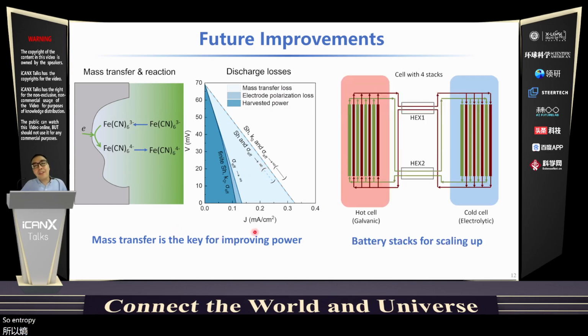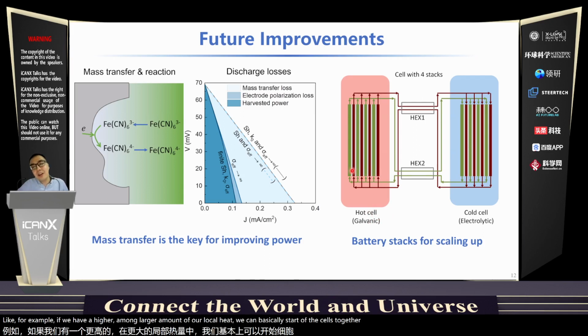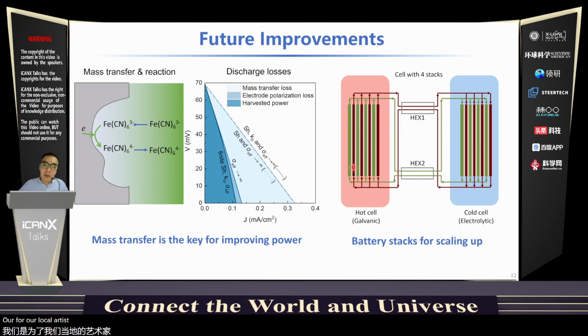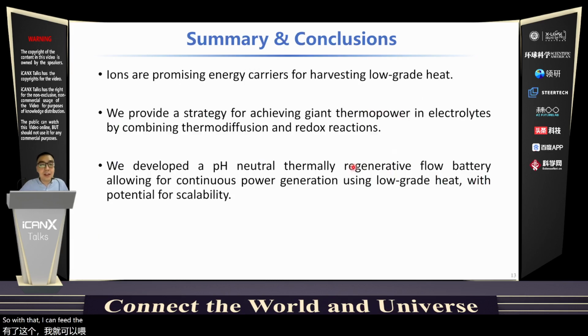After solving this issue, another point I would like to emphasize here is that this method can not only operate stably, it also has the potential for scaling up. For example, if we have a larger amount of low-grade heat, we can stack the cells together. We can scale up the power for low-grade heat harvesting. So with that, I can give the summary here. Hopefully, I convinced you that ions are very promising energy carriers for harvesting low-grade heat.